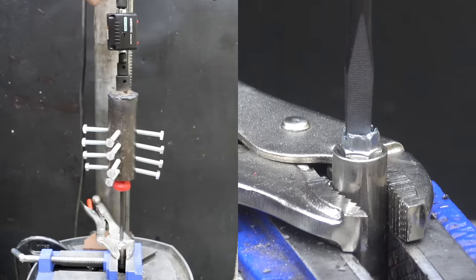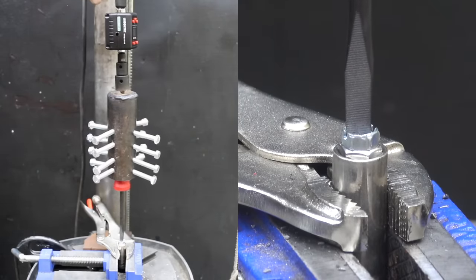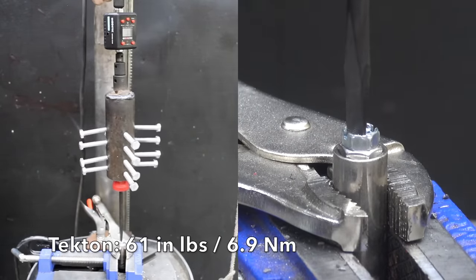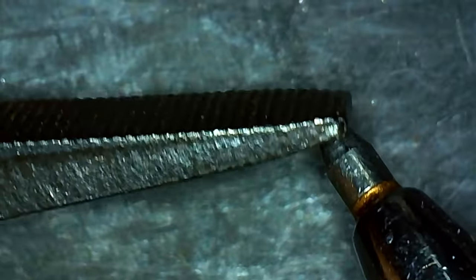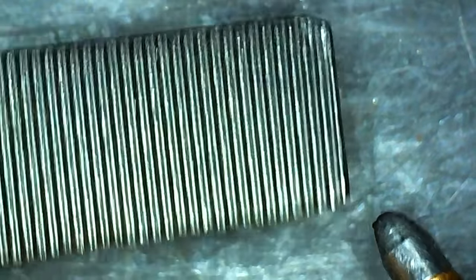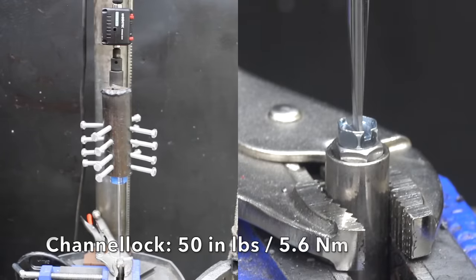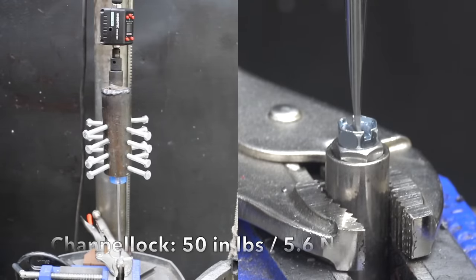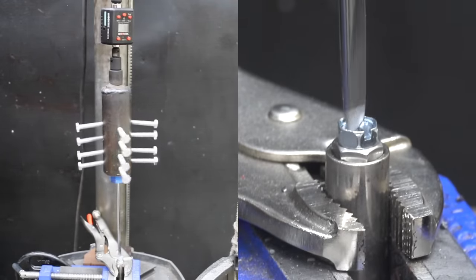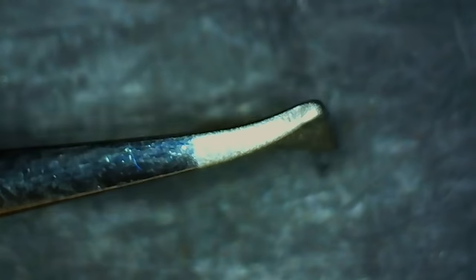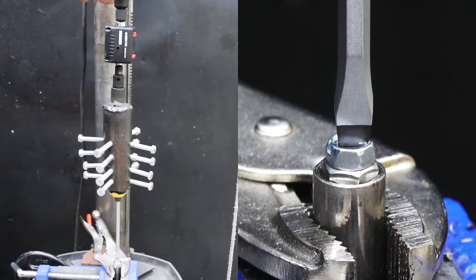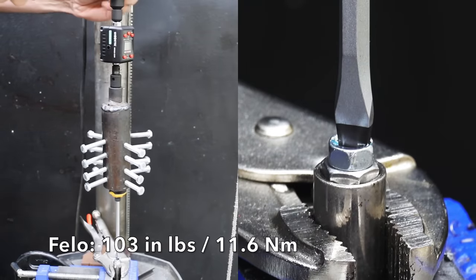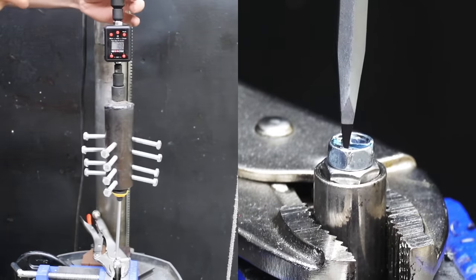The Tekton's blade is slightly thicker than the Craftsman at 1.04 millimeters and it barely edged out the Craftsman at 61 inch pounds. The blade is now bent, but the bend isn't nearly as bad as the Pittsburgh's. The channel lock screwdriver has the thinnest blade yet at only 0.95 millimeters and it gave up at 50 inch pounds. And the blade on the channel lock screwdriver has a pretty bad bend. And the Felo brand has the thickest blade yet at 1.22 millimeters, and it did by far the best yet at 103 inch pounds. No visible damage to the Felo blade.